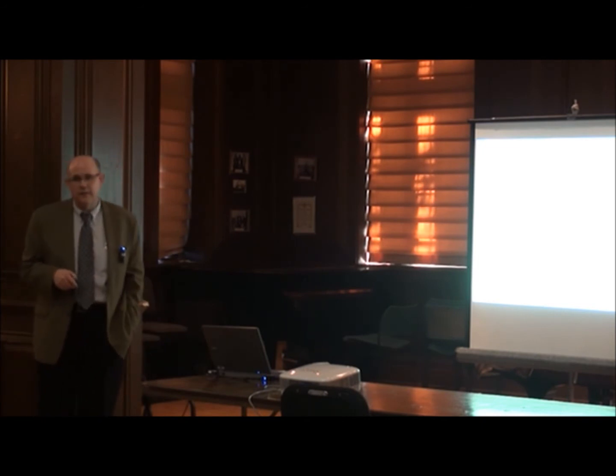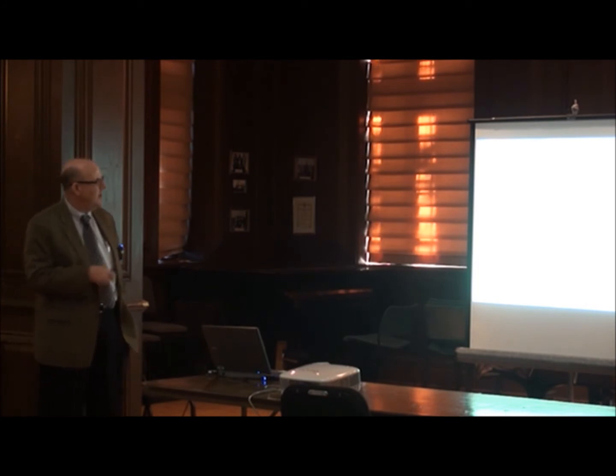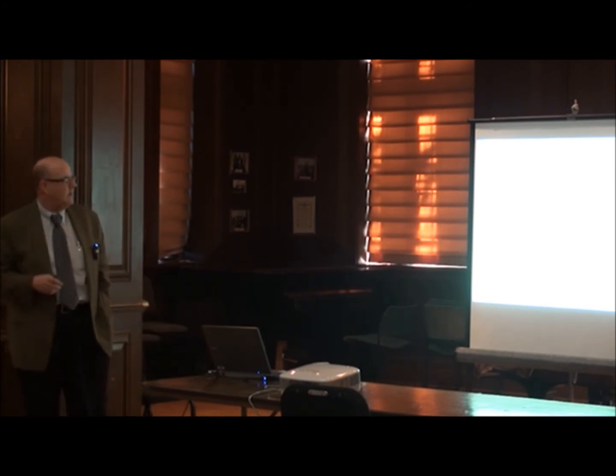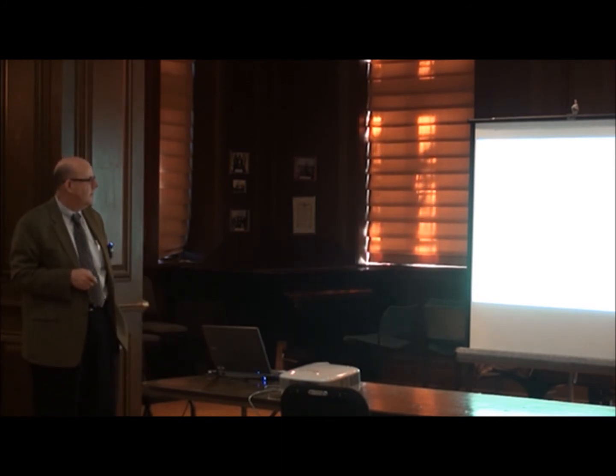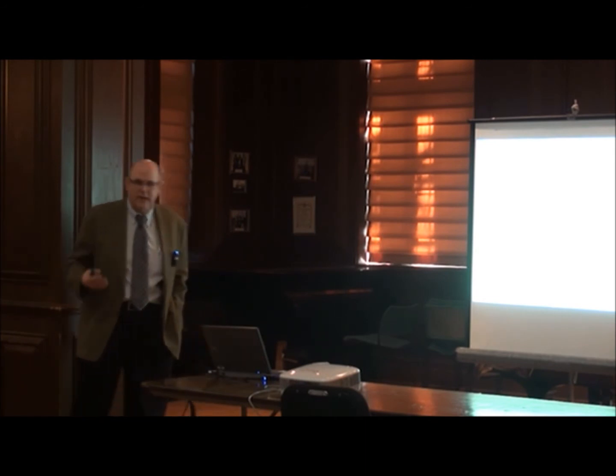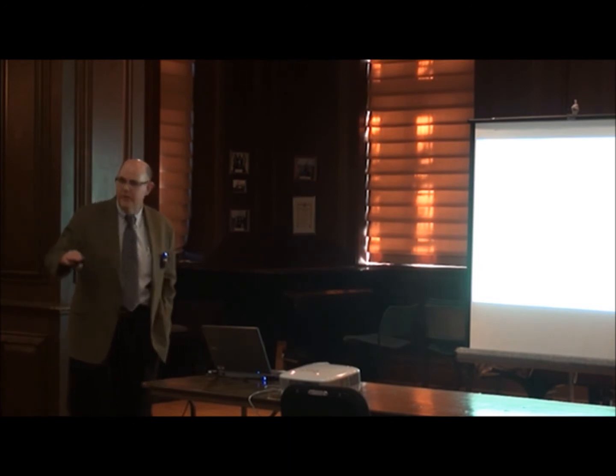The pioneering work was done in the late 70s to early 80s. Two fields of thought, if you will, two competing models. One was by this group in 1970, the other was Patir and Cheng in 78. These are the guys from Northwestern that ultimately have the lineage to Dong Zhu and Jane Wang. The key point is this: if the texture affects the flow of the lubricant through that interface, that affects the pressure that can be generated, that affects the load that can be supported, that affects the way the fluid is shearing through that interface, and that's how you affect the friction.